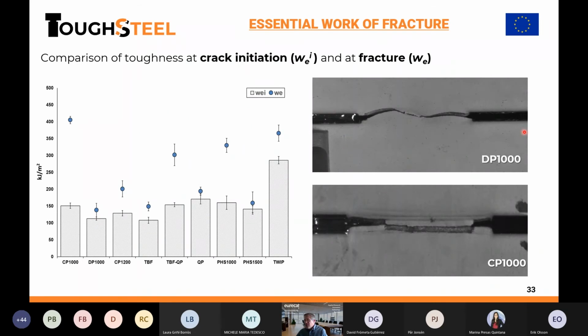And this is seen in this video. This crack grows very fast. When it starts, it grows very fast. On the contrary, if you look at that video, when the crack starts to grow, it takes a while to fracture, because the energy during propagation is higher and higher and higher. So this separation of initiation and propagation is consistent with what we see in practice: a material that can withstand crack propagation and a material that has a low crack resistance.